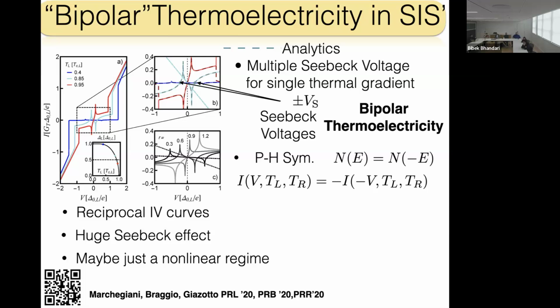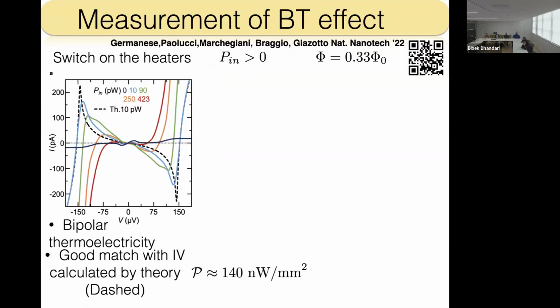And so you say, okay, this was the theory. Now can we do the experiment? And we did the experiment. It was hard, but not extremely hard. Maybe the most difficult part was finding a way, because I forgot to tell you that in this type of analysis, I am neglecting the Josephson coupling. So I need to create a system without Josephson coupling. That is really a bit strange, because superconducting tunnel junctions are typically made to make the Josephson coupling important. Now, you need to build a system in which the Josephson coupling is suppressed.